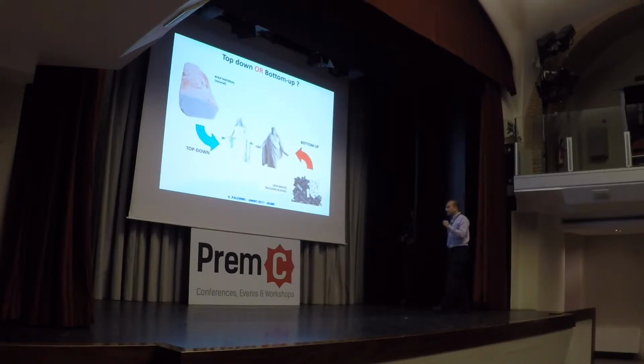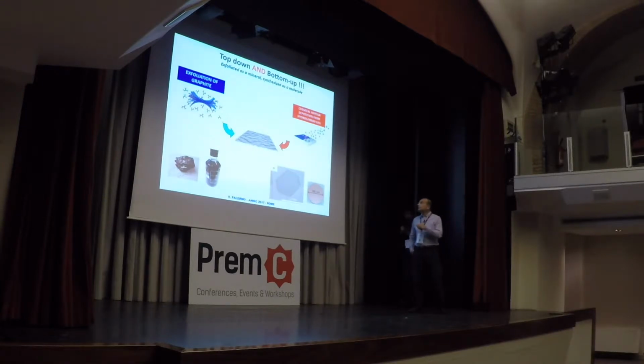The good thing about graphene, a key advantage with respect to other materials, is that you can produce it in lots of different ways, both from a bottom-up approach, like exposing a metal surface at high temperature to carbon-containing molecules through chemical vapor deposition. But we already have huge amounts of graphene in graphite. In graphite mines, this is really cheap, and what you have to do is just separate the single sheets of graphene inside graphite. It's not as easy as it seems, as I said. You need lots of energy, usually the quality is not good, but this gives you a huge versatility.